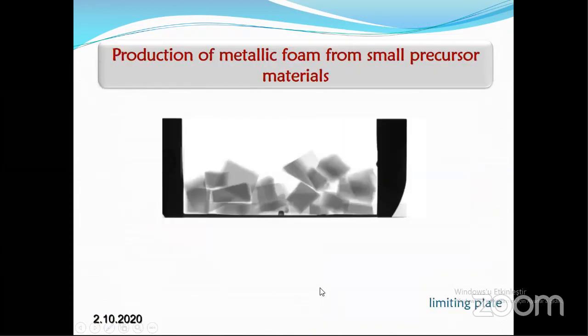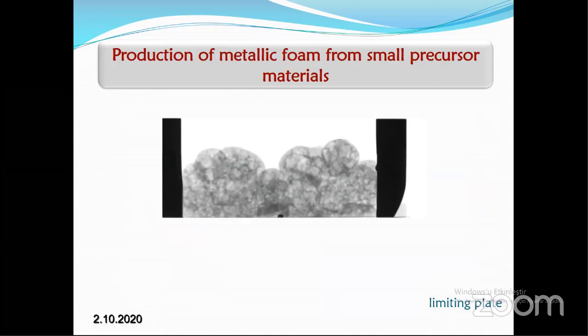How can we produce? Actually, there are a number of production methods. This is production of metallic foam from small precursor materials. Actually, we don't use these precursors so much, but just to show how metallic foam comes out. This video is very good. Okay. When you heat it, the precursor foamable material starts foaming, and then sometimes you have to take it out. If you want to control the structure, if you want to control the mechanical properties, you have to put some limiting plate somewhere here.